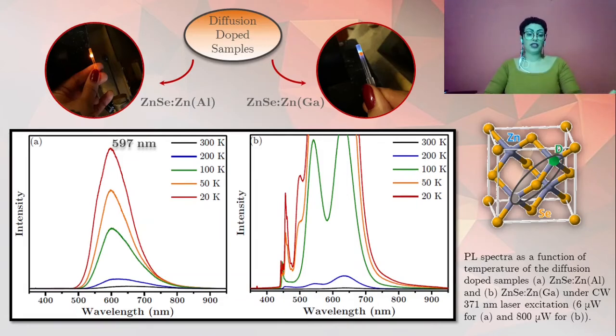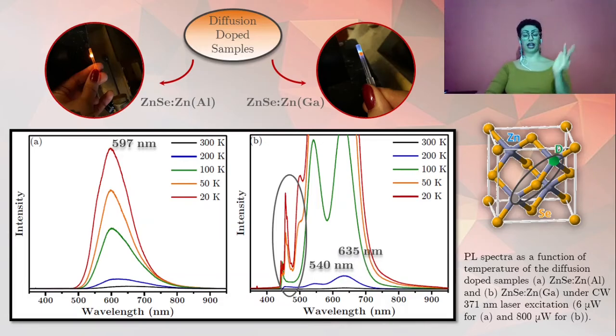For the PL measurements for the gallium-doped sample, we can observe the presence of several excitonic peaks and two broad luminescence bands. The PL band observed at 540 nanometers has already been reported in the literature as the recombination of A centers in gallium-doped zinc selenide crystals. The new band observed at 635 nanometers may also originate from radiative recombinations of other configurations of complex defects involving donor states introduced by the gallium impurity and the zinc vacancies as acceptors.